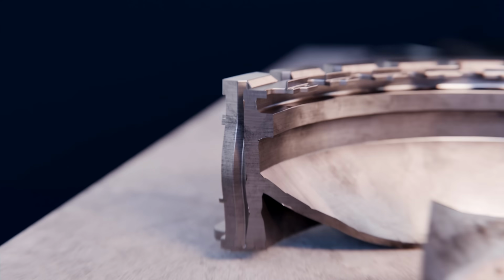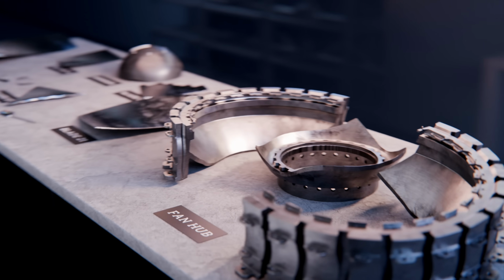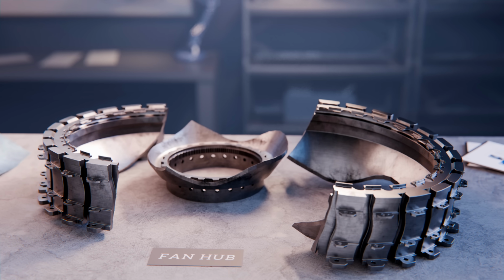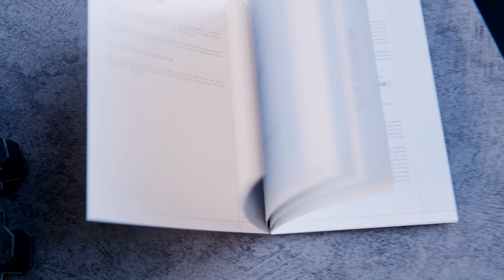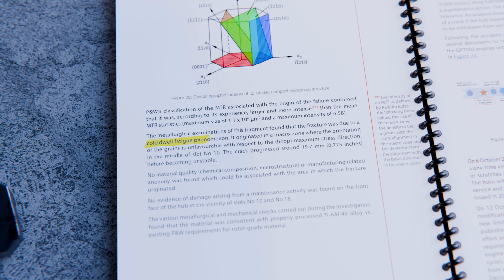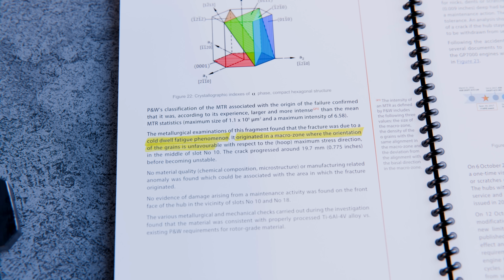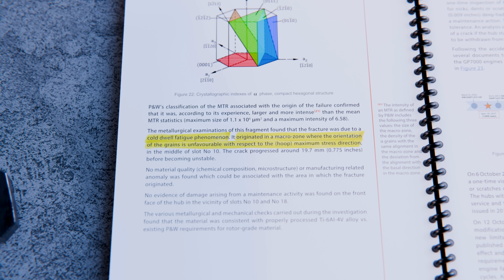And that's exactly what caused the engine failure on Air France Flight 66. The French investigators concluded that dwell periods accelerated the initiation of a crack in a microtexture region in the fan hub, which cyclic loading then grew to failure.